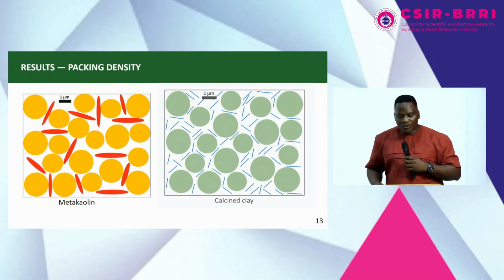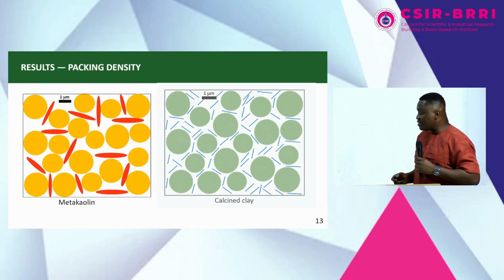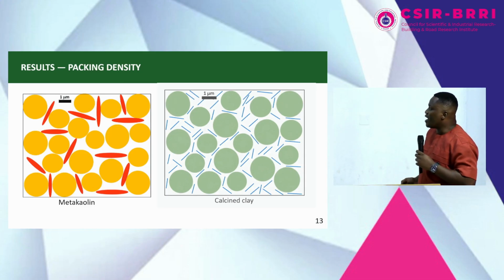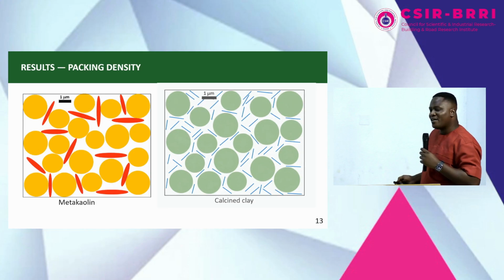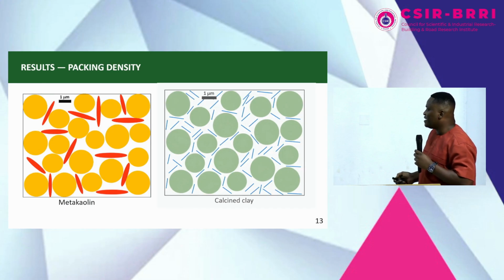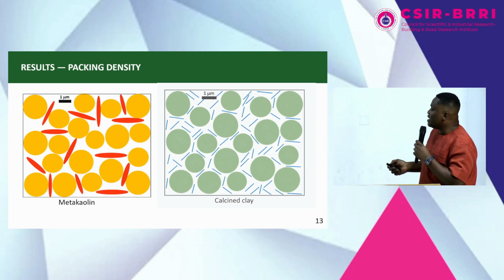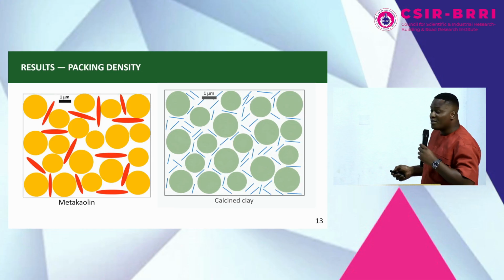All right. So straight to the results. These results are about the packing factor, or the packing density. So we have that of metakaolin here and that of calcined clay here. Straight away, you realize that the calcined clay has a better packing density than the metakaolin, because it has some thread-like materials in between the round or circular particles, which makes it more compact and less porous as compared to the metakaolin here.